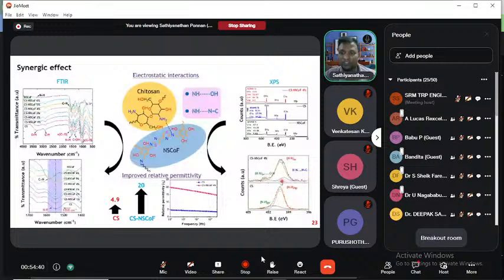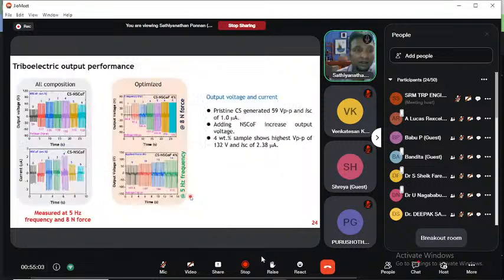Due to these two interactions, it improves the relative permittivity. We observed chitosan shows around 4.9, whereas the composite system shows around 20 relative permittivity value. So this is the proof for the synergic effect of the composite systems, and due to these effects, it produced a good amount of output voltage and current.